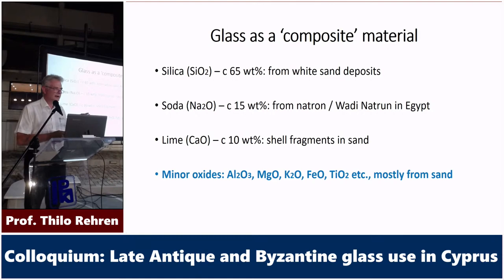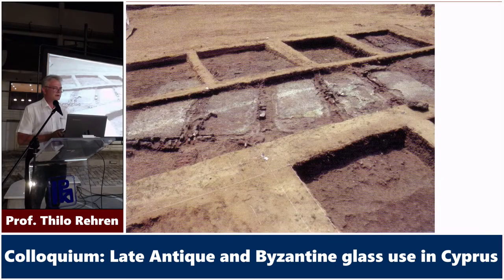We will not really have seen white sand. Most sand is yellowish. That yellow is iron oxide. You will have seen dark particles in it, which could be titanium oxide. You will have seen red particles in it, which could be aluminium-rich or magnesium-rich. So it's that little bit of flavor in the sand which is important for us, because that goes with the sand into the glass and stays in there.